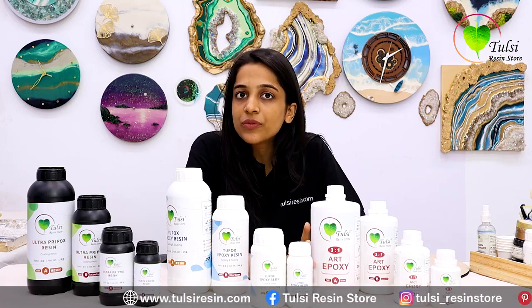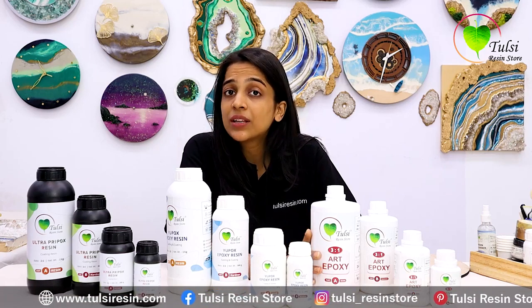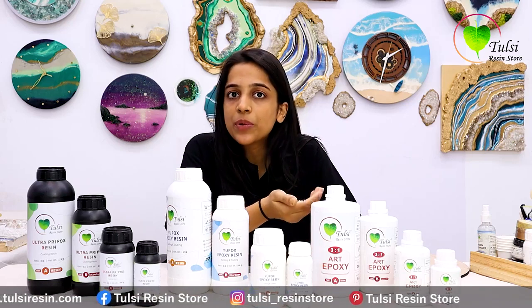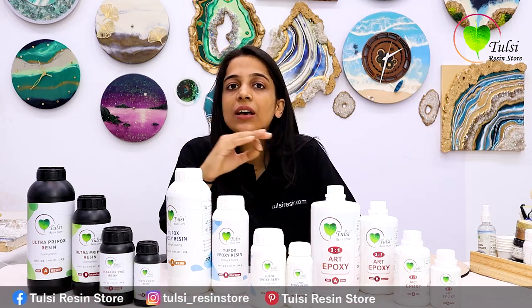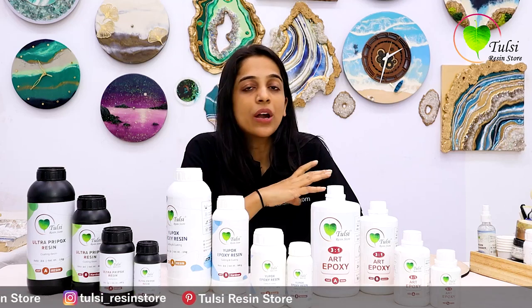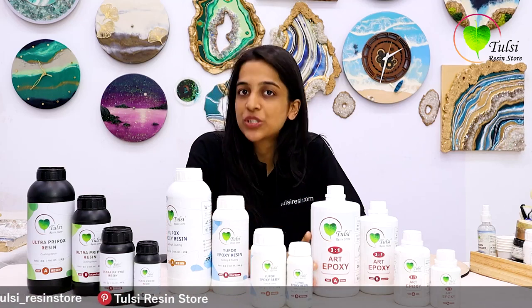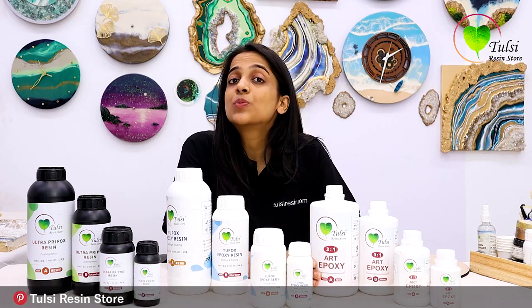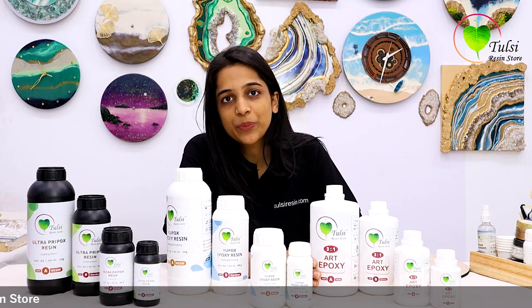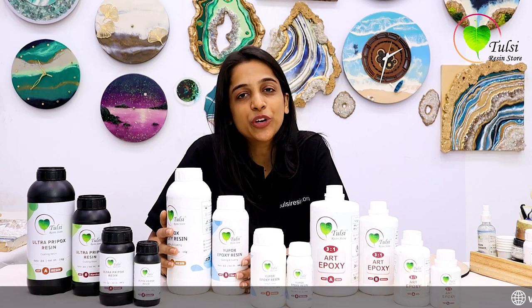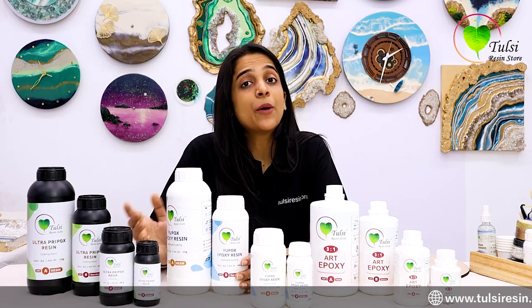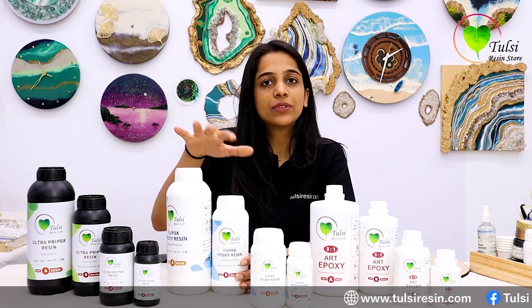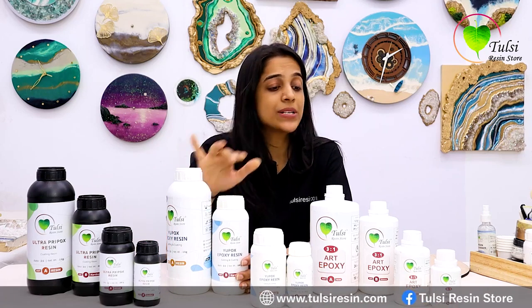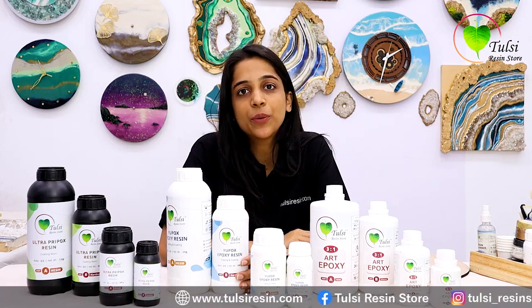But because the viscosity of this resin is very thin, when you use it you get a thin layer of resin. You do not get a dome structure because of its viscosity. That's why this resin is perfect for our casting purpose, and epoxy resin is perfect for our coating purpose. Now both the things are done. We have epoxy resin for coating purpose and art epoxy for casting purpose.